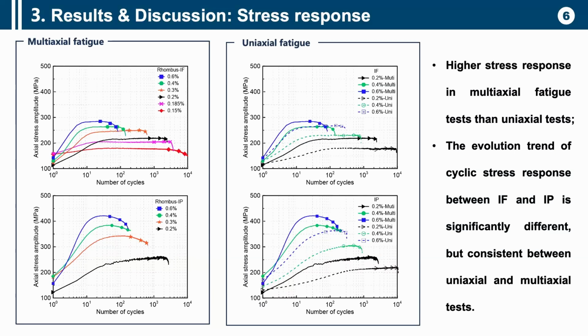For multiaxial loading, the stress is higher than for uniaxial loading. This is for IF, and also for IP: the multiaxial loading shows a higher stress response compared with uniaxial loading. It means that under non-proportional loading, there is some additional hardening.